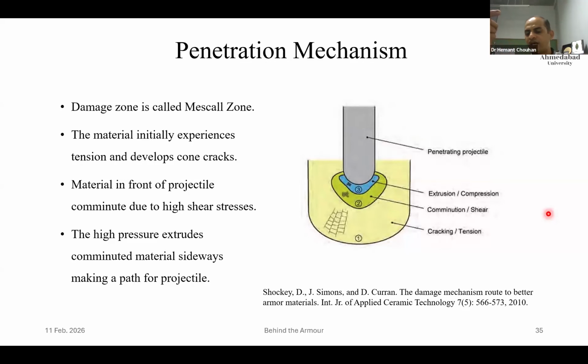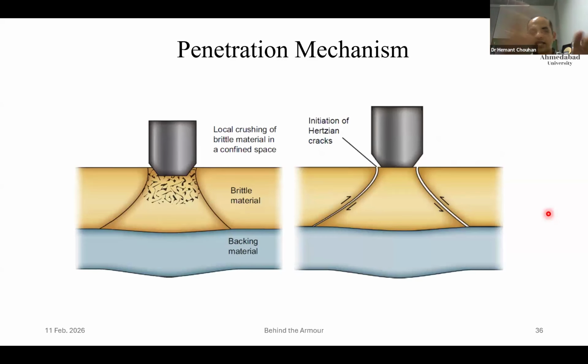If this does not happen, then we are going to face a challenge. In another study, they mentioned that this is the comminution zone. The crushing will happen in front of the projectile, and there will be a crack growing from the tip towards the back, and this is where we see the tensile deformation of the ceramic. If this tensile deformation is allowed because of lack of stiffness of this composite backing, then your crack will grow very fast, and in that case the projectile will enter, and there will be a shear plugging phenomenon happening throughout the object, because in any case this composite backing has got no strength or no hardness to actually deal with the hardness of a hardened projectile.